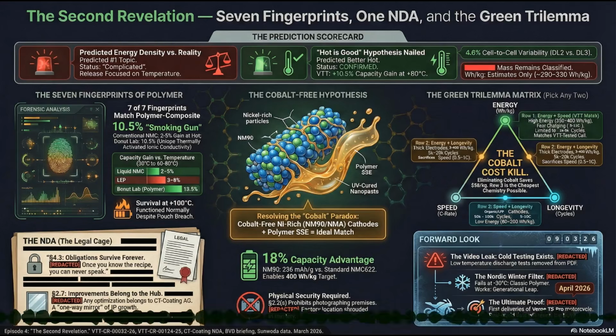Which means it swelled at 100 degrees and continued to function is an incredible data point for thermal tolerance. But it is absolutely not the same thing as a clean pass. Gas generation changes the internal pressure dynamics of a cell. It can cause microdelamination between the solid electrode layers, increasing internal resistance over time and severely compromising long-term cycle life. So it's not just a wrapper issue. We cannot simply wave away the swelling as a melting plastic bag. The physics strongly suggest it very well could be the underlying chemistry groaning under the immense thermal stress.